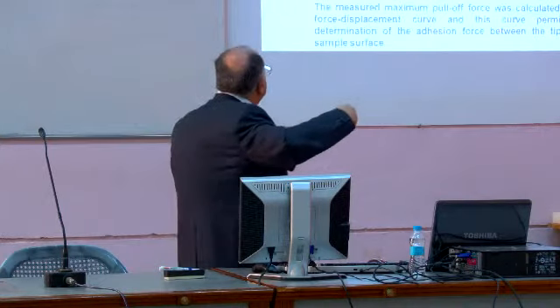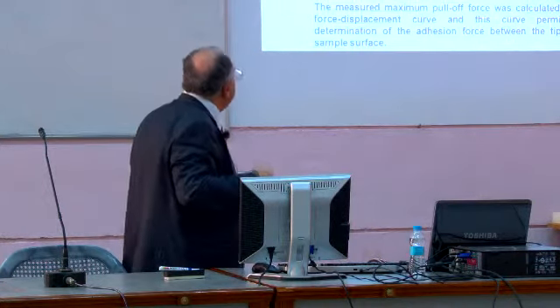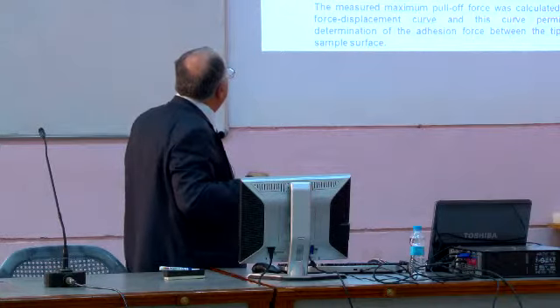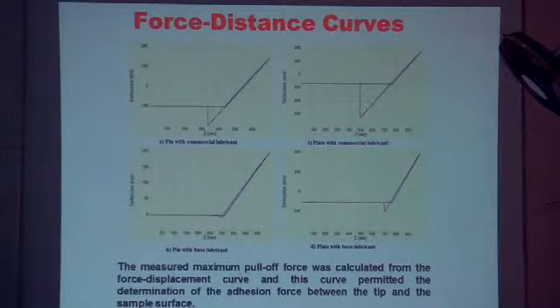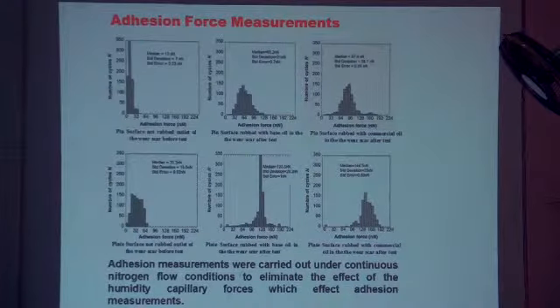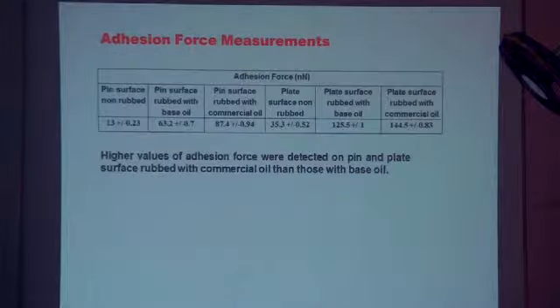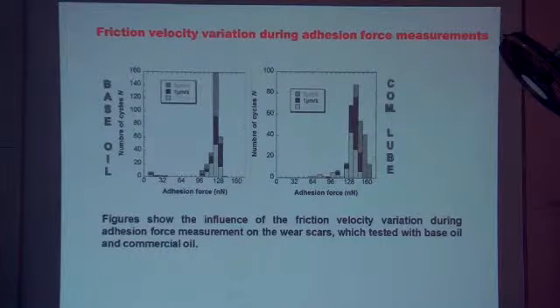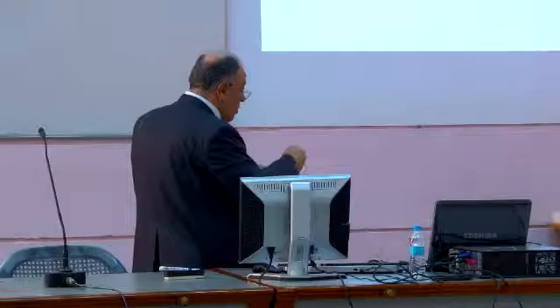And we did some force-distance curves. We found more force for the test carried out with commercial oil, where there are additives. We also did adhesion measurements, and these showed higher forces on the surface of the pin and plate for tests carried out with commercial oil than with base oil. Even the adhesion force measurement, and also the friction velocity etc., you see it is much higher than with base oil.